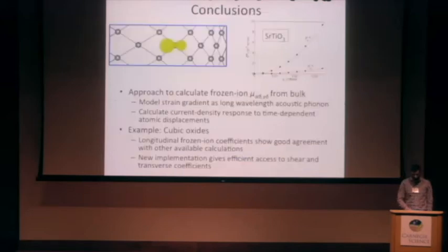So just to conclude, I've given you a brief overview of our approach for calculating the frozen ion flexoelectric coefficients by modeling a strain gradient as a long wavelength acoustic phonon and calculating the current density response, and then given some examples of cubic oxides. Thank you.